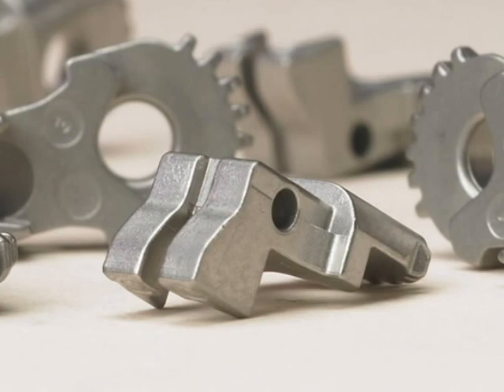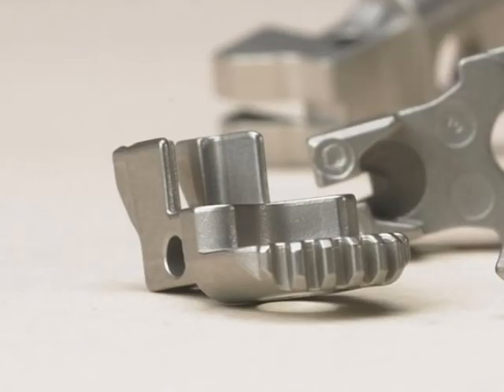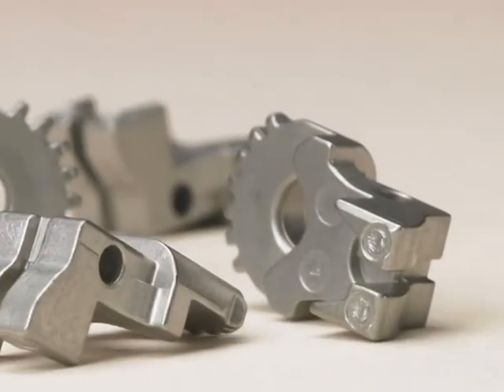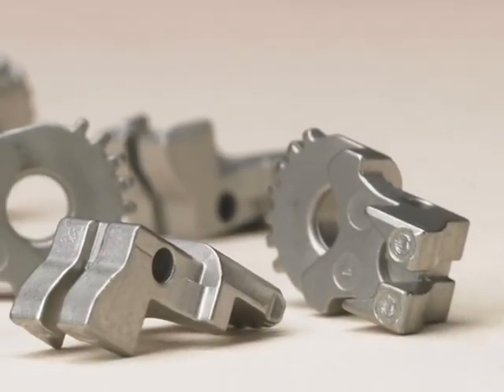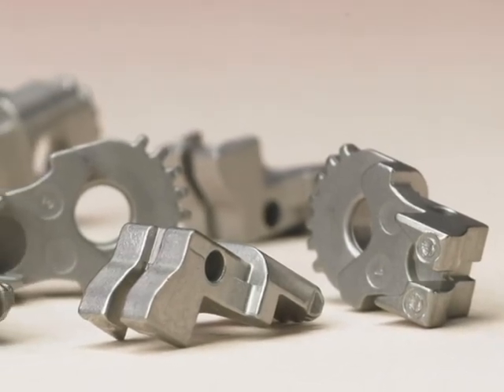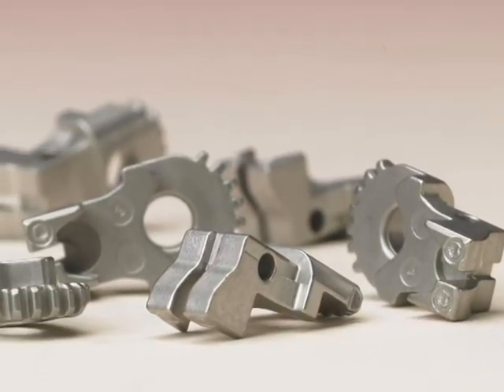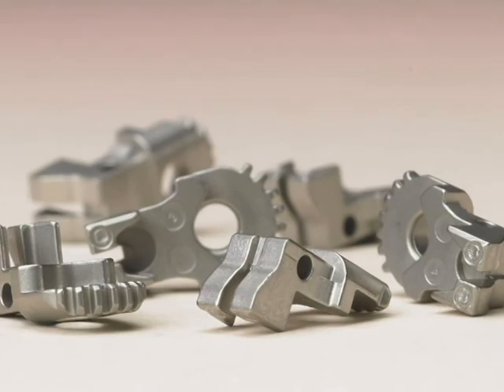Formed to a typical density of 7.7 grams per cubic centimeter, the part has a typical tensile strength of 175,000 psi, yield strength of 158,000 psi, and a 6% elongation. The MIM process provided a cost savings in the range of 25 to 30% versus other design options. Kinetics performs precision sizing and reaming.